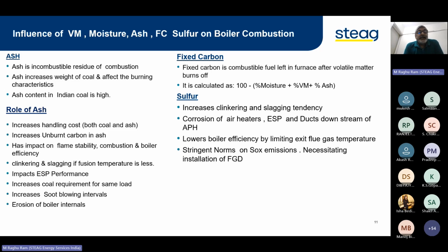But the role of ash, as I have already touched on, is that it influences your flame stability, combustion, boiler efficiency, clinkering, and slagging if fusion temperature is low. It impacts ESP performance, since with high ash content the ESP doesn't function properly. It increases coal requirement for the same load. Erosion is one of the major mechanical problems, because ash is a highly erosive component and will erode away the boiler tubes. Boiler maintenance engineers will appreciate this point, because day in and day out they see it in the economizer, water walls, or even second pass components. Severe erosion will be there in ducts also.